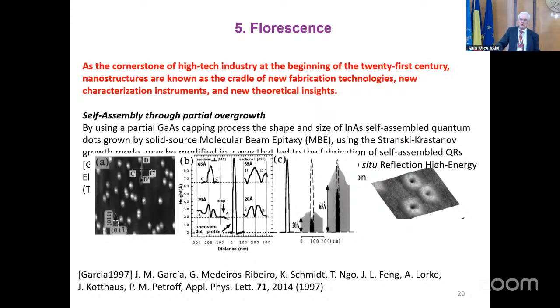To the surprise of this group, they observed such objects, which are shown in the last panel. You all see it in front, and there are some holes inside. These are quantum rings, because the sizes are a few tens of nanometers. But they were grown in one run on the whole wafer. It was not a fabrication of an individual ring, but a fabrication of an ensemble of rings. But I emphasize self-assembly. They were not controlling any of these rings. They were providing the possibility for rings to grow everywhere.